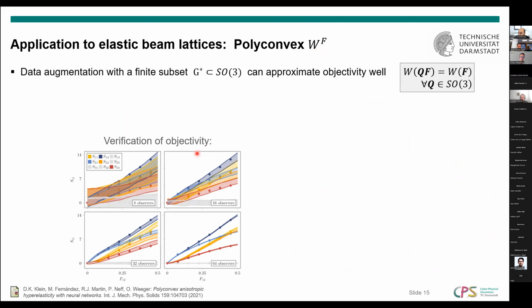But for this model, we cannot have objectivity in a hard-coded, or hard-implemented way, so we use data augmentation. That means basically now we have our data, for instance, of uniaxial tension. We choose 8 rotation matrices, 8 other observers with which we enhance the data set, and then we train the model on this data. And what you see in this plot here is now the evaluation of the model for a total of 1,000 randomly chosen observers, and the lines basically indicate the worst case predictions.